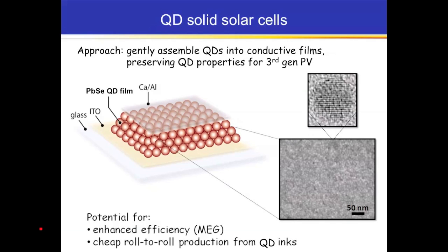What we're trying to do here is to make PV devices that use as their active layer a thin film of conductive quantum dots. And the prescription that we need to follow is that we need to really gently assemble these quantum dots together in a way that does not destroy their individual quantum dot nature. So you need to retain their size, you need to retain their shape so that we keep their band gap, and also keep their ability to do multiple exciton generation intact.